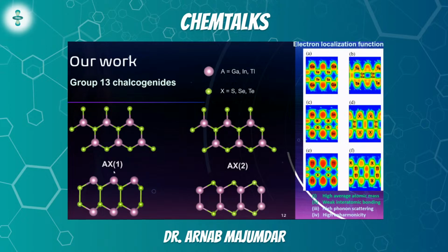But it will not be the ground state structure, it will not be the minimum energy structure, it will be a metastable structure. Nevertheless, it's also a very interesting structure. And I had my hunches. When I saw this material, we had this hunch that perhaps due to a few hints, maybe we might get a low thermal conductivity. Already for AX2, which has been studied extensively in literature, the thermal conductivity was already quite low. Maybe not very low, but quite low. Compared to graphene, yes, very low. But could we decrease it further in AX1? And this was the structure that we particularly studied and compared with AX2, which has been reported plenty of times in literature.